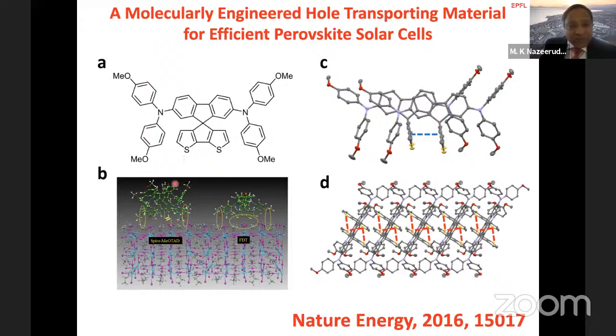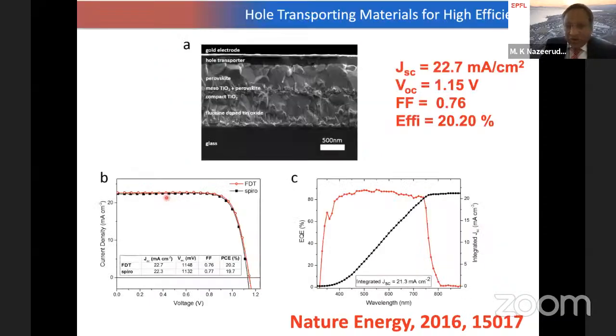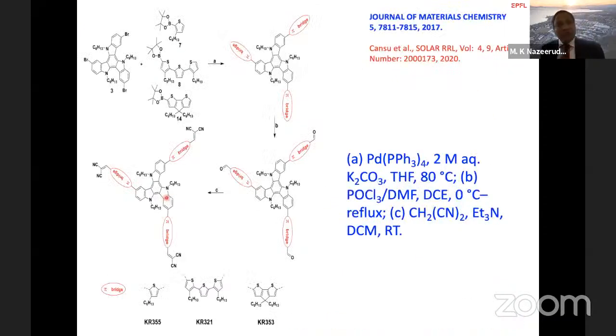but the beauty here is that it binds to the perovskite, as shown in these DFT calculations. If you look at spiro-OMeTAD, the interaction is very weak, through the oxygen and the perovskite. In the case of the new hole transporting material, you have thiophenes which interact strongly with the perovskite, passivating the vacant sites, and it also interacts with the methoxy groups, similar to spiro-OMeTAD. So this is the lesson we have learned, and then we went back and redesigned the molecules to have a dopant-free hole transporting material.